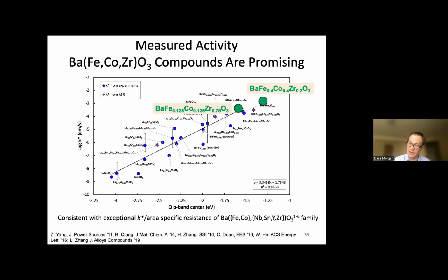There had been some previous studies of members of this family, but what was really interesting is our calculations told us that we should be able to make a material that was highly active and had a lot of zirconium. Now, if you don't have a lot of intuitions about these materials, this isn't probably surprising to you, but in the limit of having a whole lot of zirconium, this is 75% zirconium on the B site. In the limit of 100% zirconium, this material would basically be barium zirconate, which is an insulator. It's actually used as an electrolyte. So it shouldn't work really. And most people would say 75% zirconium is just too much.